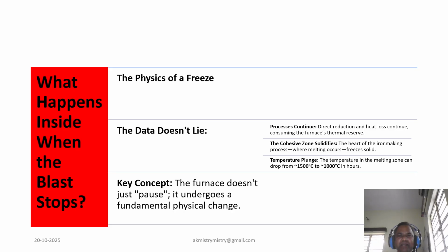First, key chemical reactions like direct reduction continue, rapidly consuming the furnace's precious thermal reserve. Its internal heat bank starts to drain. Then the heart of the entire ironmaking process, the cohesive zone, where the raw materials finally melt, solidifies. It freezes solid. The temperature in this critical melting zone can plunge from a white-hot 1500 degrees Celsius to a relatively cool 1000 degrees in a matter of hours. The key takeaway: the furnace doesn't just pause, it undergoes a fundamental physical change. It becomes a different beast entirely after stopping.